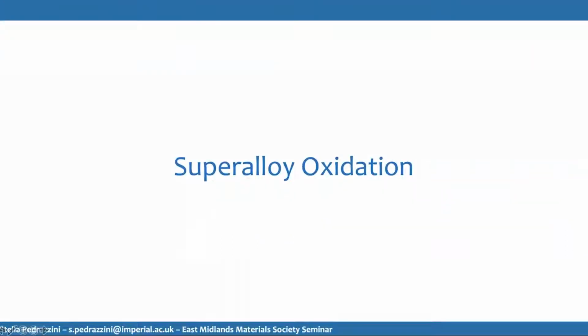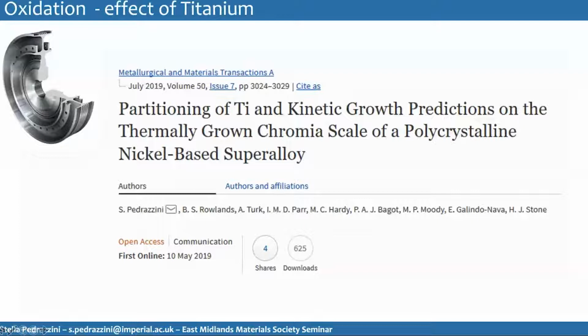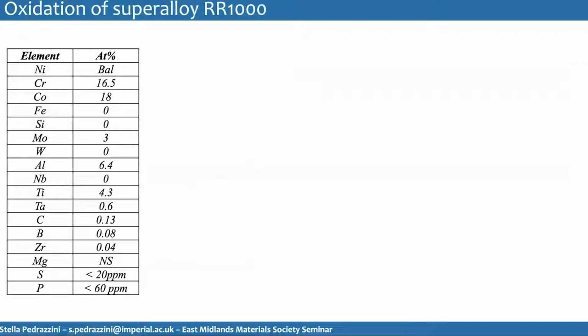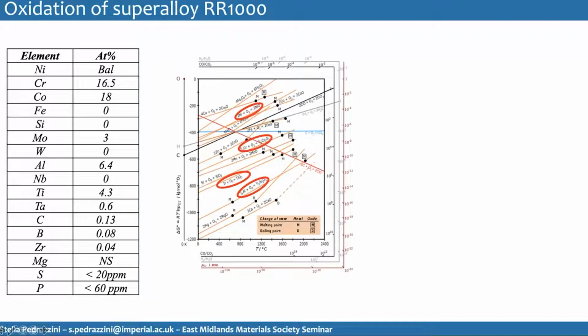And yeah, so let's move on to how this is used for superalloy oxidation. This is one example that I'm going to be talking about. This is a project that was published, that was run with Rolls-Royce, with Mark Hardy, looking at the partitioning of titanium and kinetic growth predictions on the thermally grown chromia on a nickel superalloy. So we started with the baseline alloy with some chromium, nickel, iron, no, not iron. And the oxides that were expected to form would have been nickel oxide, chromia, some titania, and some alumina.